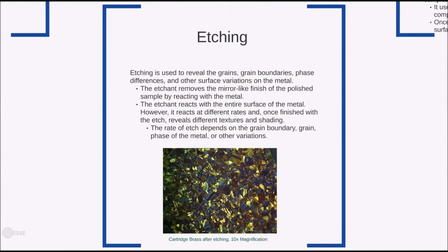It uses a solution of distilled water, ammonium hydroxide, and hydrogen peroxide to react on the surface of the metal sample. It reacts with the entire surface of the metal, but it reacts at different rates and reveals different things. For example, it etches at the grain boundaries relatively quickly, so it is very easy to see those. It reacts at twins and phase differences slower, so it must be etched for a longer amount of time to